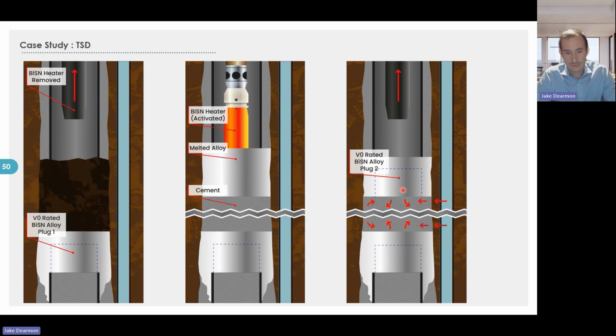One of the challenges here was that we needed to customize and have tools available on site so that once this logging was done, we could change the amount of the alloy, because we didn't know the open hole sizes that we could deploy on the fly in a remote location. So we were able to send up a variety of heaters with the alloy in a pelletized form so that based on the log results, we could adjust the amount of alloy we intended on melting in a particular zone based on the actual open hole log dimensions in that zone. So we had to have some versatility in the tool functionality that we sent.